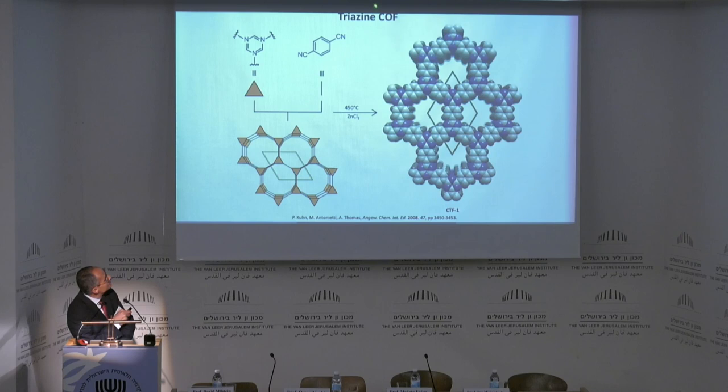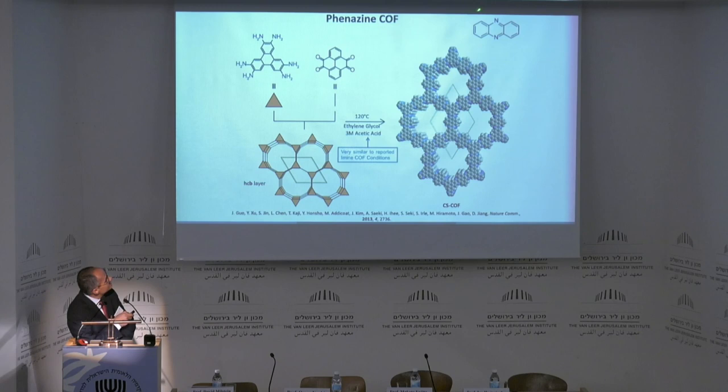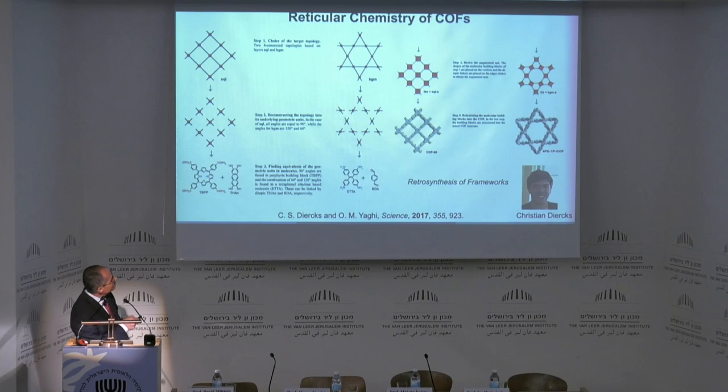Polyimides, phenazines, okay? And so really, just like molecular organic chemists do retrosynthesis on their molecules, now we are doing retrosynthesis on frameworks, where we imagine the nets, decompose them into their building units, look at the angles between the building units and within the building units, pick the molecules that you need, and then assemble them into the framework. Unlike MOFs, here we know the structures that are going to result, or at least we have good candidates. We simulate their X-ray powder diffraction and then match it to what we get out. And that gives you a good starting point for solving their crystal structures.